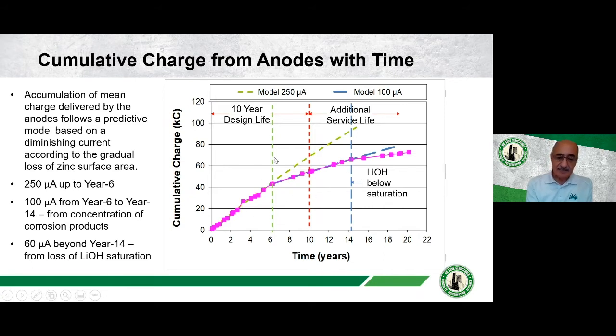So what caused that? The speculation, as far as I'm concerned, I think it's probably correct, but we're checking that out, is that the corrosion products became so numerous and they were starting to block the pores sufficiently to restrict the current from flowing freely. So there was a sudden critical concentration of corrosion product, which reduced the porosity significantly and started to slow down the current density. So that's what that one is. So we get a profile which looks like that. Considering that we were working on a 10-year service life, I think we pretty much got it right in terms of predictive current output.